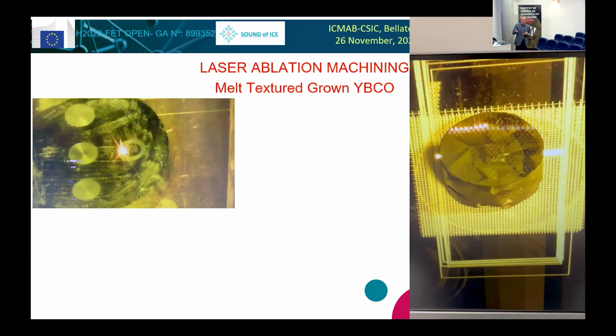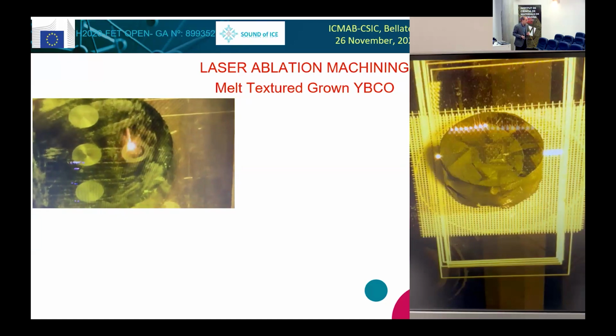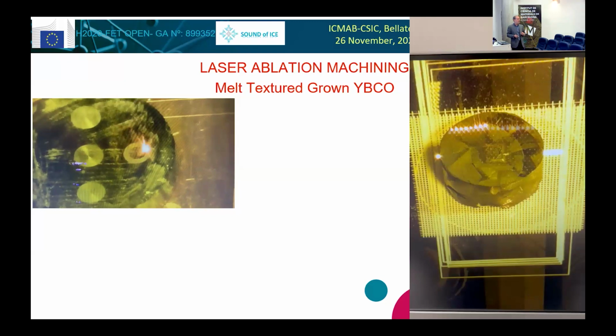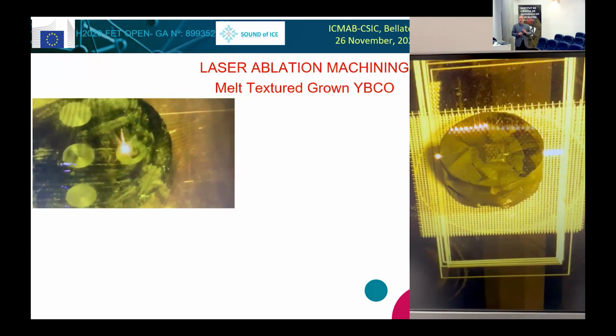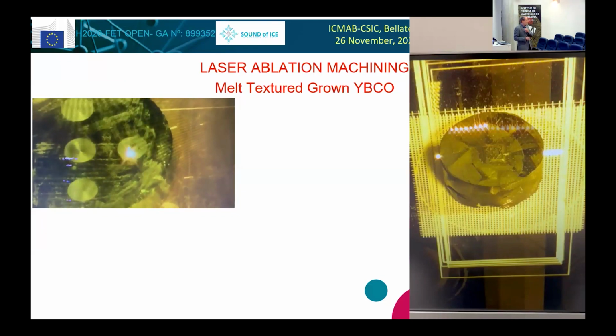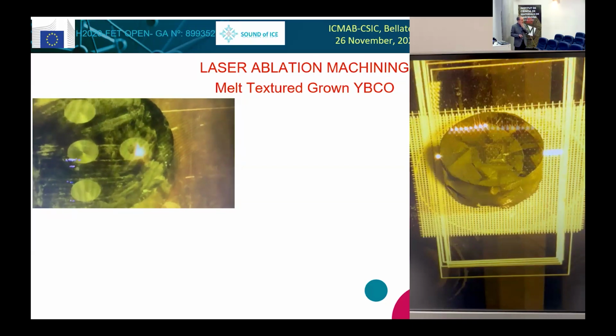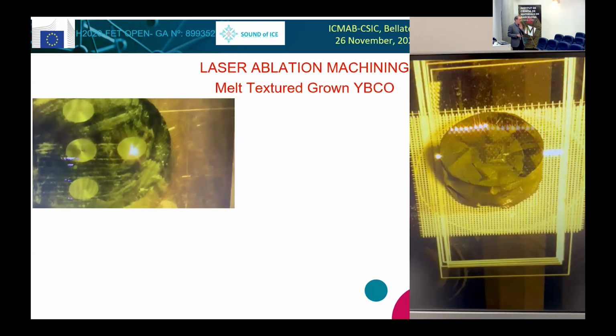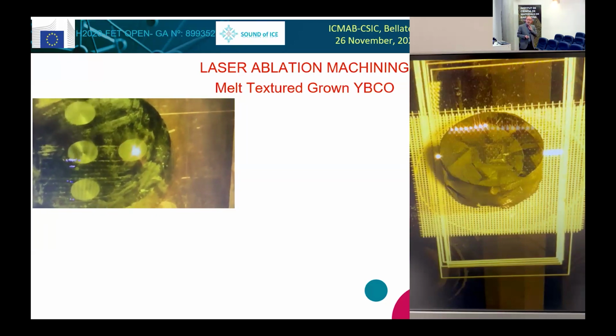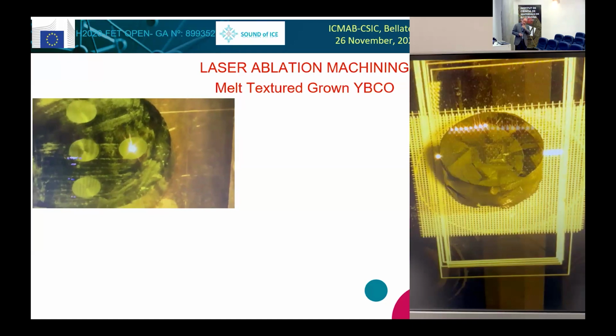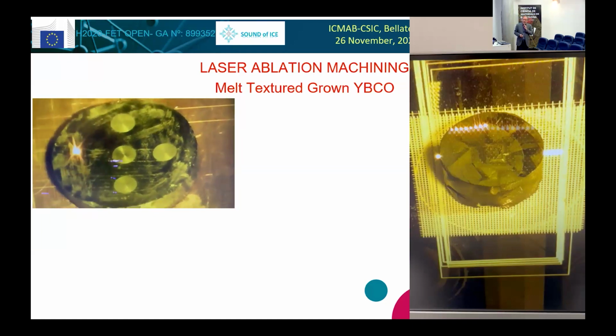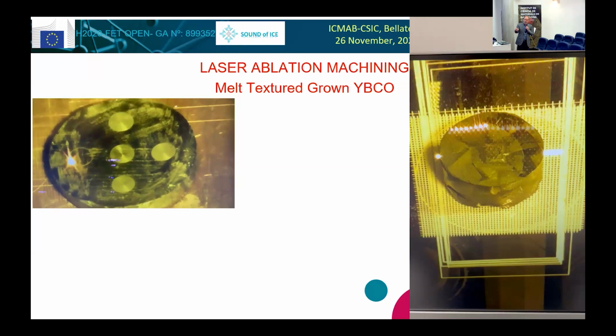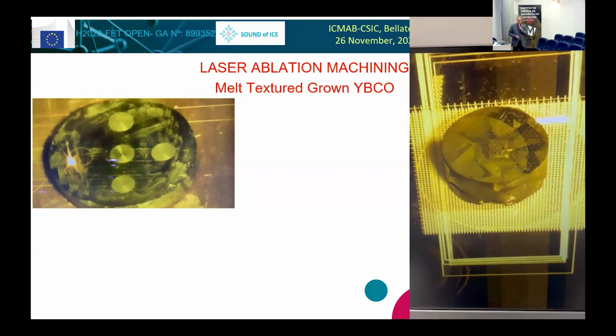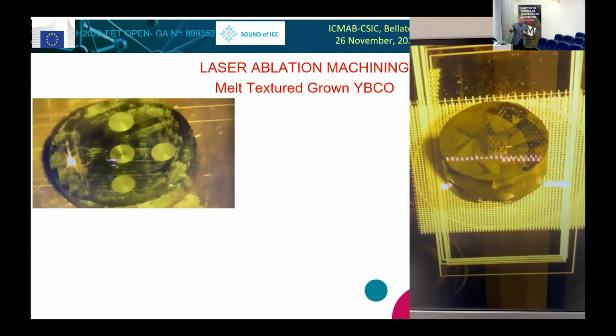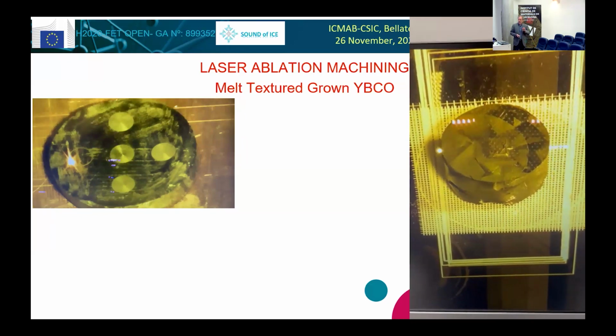Here I show you other things we can do. Textured YBCO. You can see we can now do ablation. This is really ablation. So we are machining this superconductor, which is not easy to machine without damaging it. So this we can machine with a femtosecond laser. This is done with a UV wavelength, and you see I can do any type of geometry.